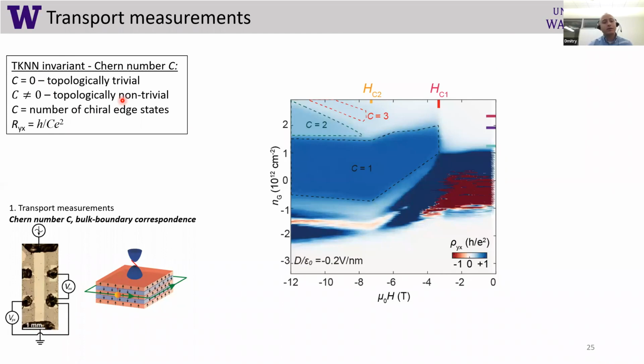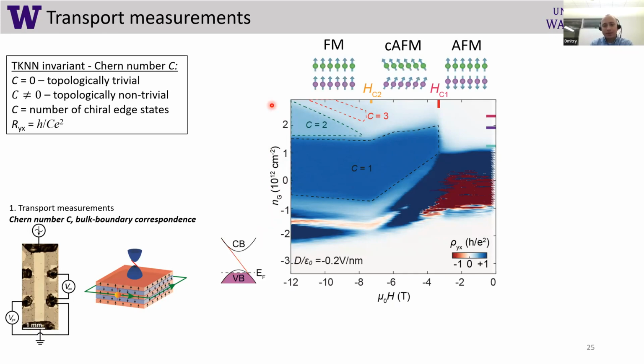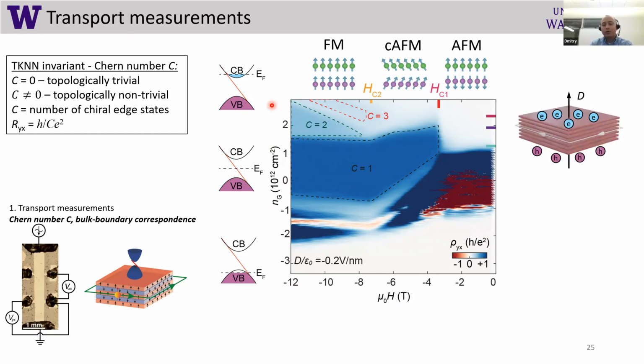And in our devices, we have a lot of tunability. So essentially, we can change gate voltage in our materials. In this case, our materials are atomically thin. We can change gate voltage and move in our band structure. We can also change magnetic state with external magnetic field. Our gate allows us to walk through a valence band, gap, and conduction band. And we also have, in some of the devices I'll be showing you, the way to control the electric field. So we have dual gate geometry in which we can apply electric field and control top and bottom surface simultaneously. For example, we can essentially get only electrons to both top and bottom surface, or no charges, for example.